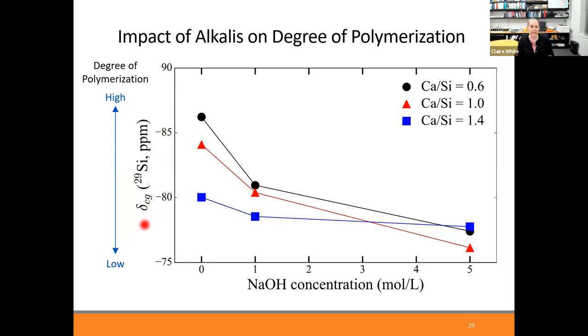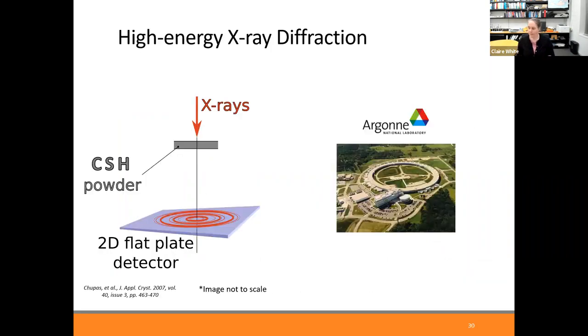And what you can see is this center of gravity decreases for all of the different compositions, which is showing you're going from a high degree of polymerization when there's no sodium to a lower degree of polymerization when there's more sodium. So what this means is you're getting shorter chains of the silicate units when sodium is present, which could make the structure more prone to degradation, which is not a good thing. However, I will talk a little bit about the role of alumina that can combat these shorter chain lengths. So if you have sodium and alumina, this can lead to similar chain lengths to the normal CSH gel. What we also did was X-ray pair distribution function analysis on the same gels.